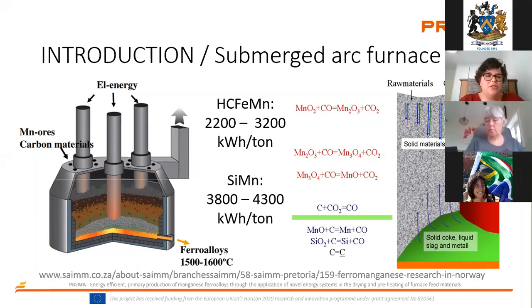And by the time it reaches the wet coke bed, which consists, as I said, of slag, liquid slag, and carbonaceous reductant, you have your iron, that's if you have a properly operated furnace, that's already Fe, metallic iron, and you have your MnO that dissolves in the slag and then forms where the final reduction takes place of MnO to Mn. Your quartz also dissolves into the slag, and from there it's reduced to silicon. And you have carbon that dissolves into the alloy.